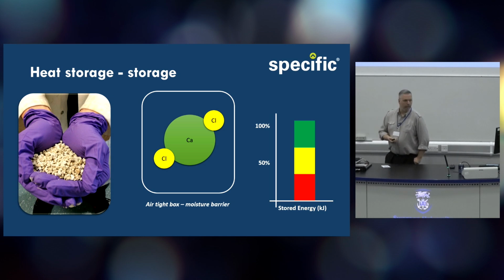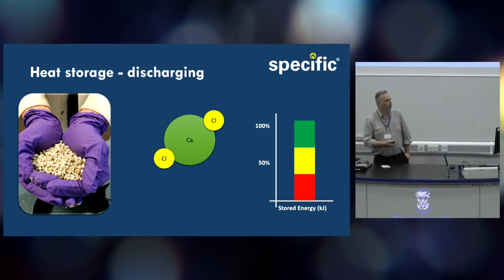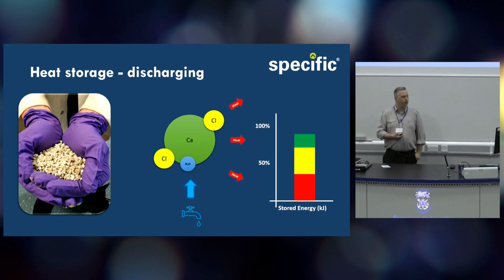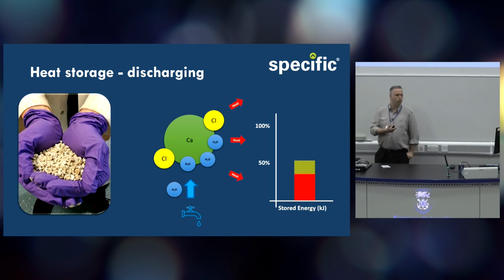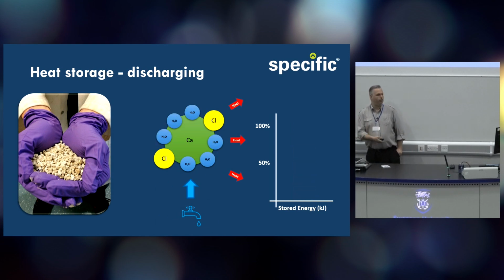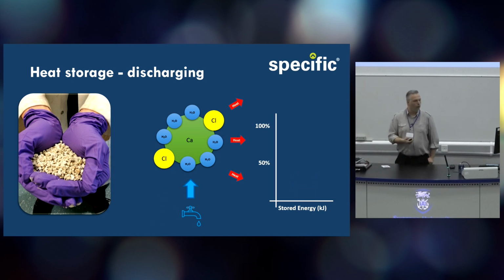To recover that energy, all we need to do is put a moist air stream through it. The moisture recombines with the salt. That's an exothermic reaction, so it gives out heat, and we can transport that heat from the point of generation through to where we would actually use it, as I say, whether that's space heating or a pre-feed on the process.